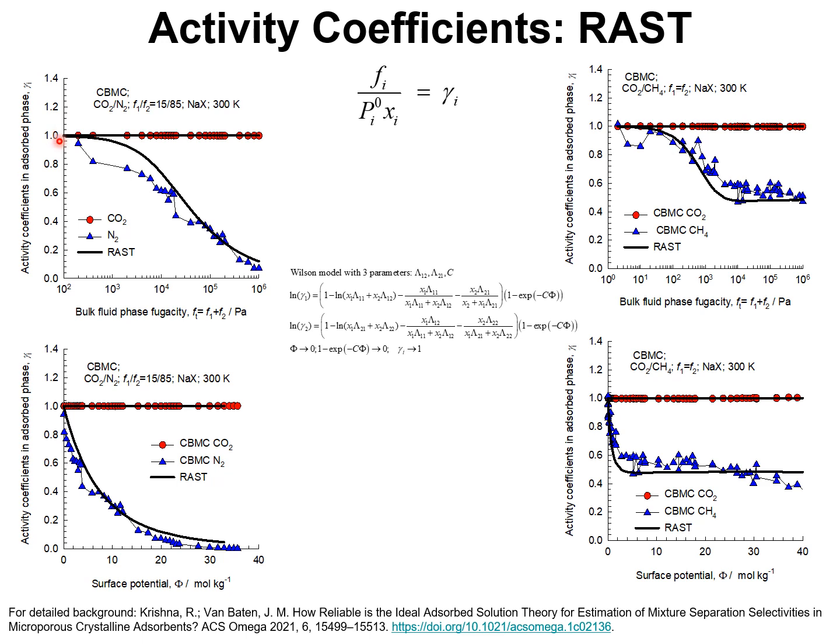Indeed, this must be true because at very, very low pressures, the component loadings in the adsorb phase would follow the IAST calculations accurately. Deviations from IAST will manifest as the pore occupancy increases.